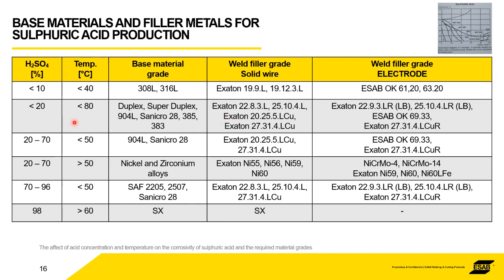So even up to 80 degrees, for example, we can use things like 385 and 383, and these exist in both solid wires and also in covered electrodes. So these are very high alloys. This is 27 chrome, 31 nickel, 4 molybdenum with low carbon and with copper. So it is available as a rutile electrode, for example. Similarly with 385, 383, 2025-5 LCU or an OK 6933.